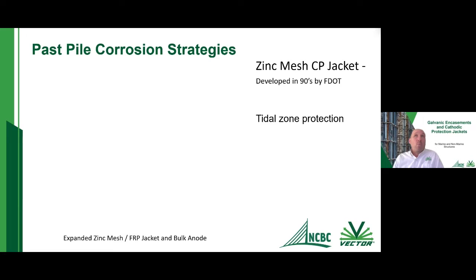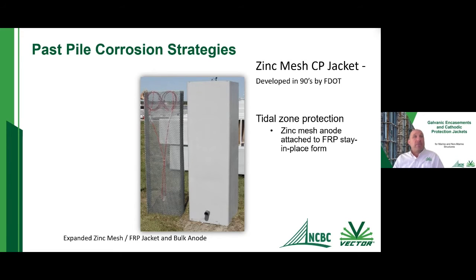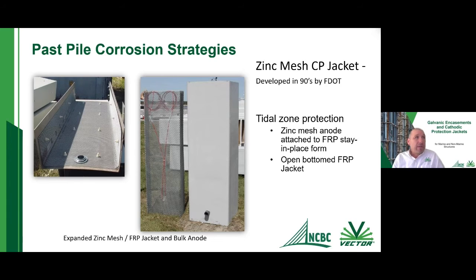So one of the CP jackets that was developed, Florida DOT in the 90s developed an expanded zinc mesh jacket that was placed inside of a standard fiberglass stay-in-place form. This zinc mesh is attached to the inside of the fiberglass jacket, and it has basically an open bottom, so it allows water to go up inside of this jacket.